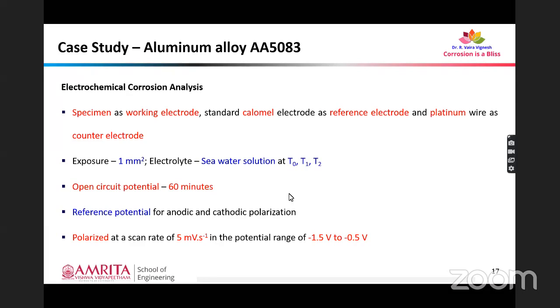Then we have to establish open circuit potential for 60 minutes. That is, we have to leave the setup for 60 minutes completely and measure only the potential that is coming out of the working electrode. That is the potential that is set up between the working electrode and the reference electrode. That is what we have to measure. Once this open circuit potential becomes stabilized, we can go ahead with potentiodynamic polarization scans. This OCP will be used as the reference potential for anodic and cathodic polarization.